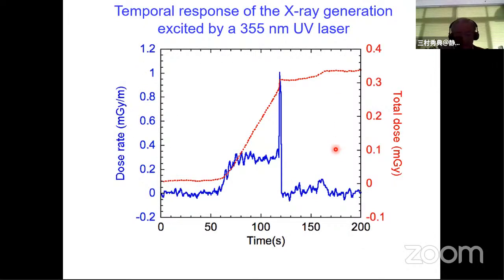This slide shows the temporal response of the X-ray generation excited by the 355 nanometer UV laser. In this case, the maximum dose rate of about 1 milligray per minute was obtained, and the total dose of 0.3 milligray was obtained over 200 seconds. The dose rate is one third lower than that of the direct excitation of the lithium niobate crystal using the 266 nanometer laser light.